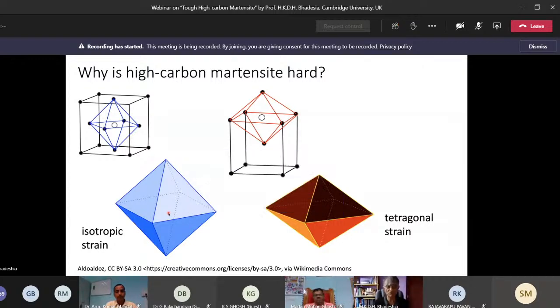And a uniform expansion has a very weak interaction with a dislocation strain field, because the purpose of a dislocation is to shear, so the majority of its strain field is connected with shear strains rather than just a volume change. So carbon has a small effect on the strength of austenite because this octahedral interstice is regular, and therefore it causes a uniform expansion which has a weak interaction with dislocations.